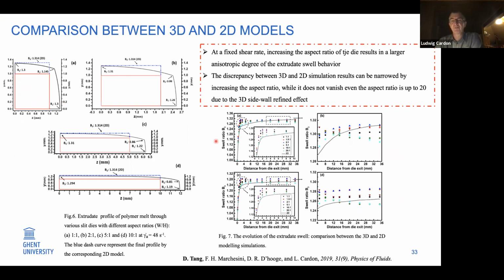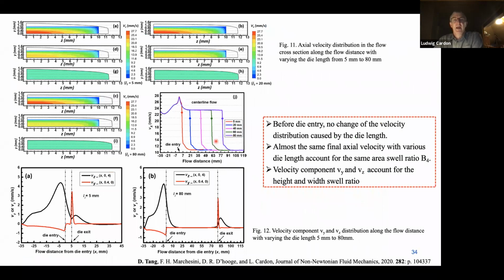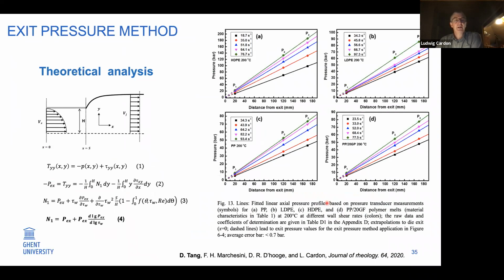the 3D and 2D models, which we developed, and to find out finally if it's possible to predict it on a 3D level, which is important not only for the flow behavior, or the visualization, it's also very important in the scope of the behavior of your polymer inside finally the extruded part. So you see some ideas here of what finally happens depending on our center line, depending on the width of the die, and so on, the effect of the die swell itself. I pass by a little bit faster to avoid lack of time for discussing also other topics.